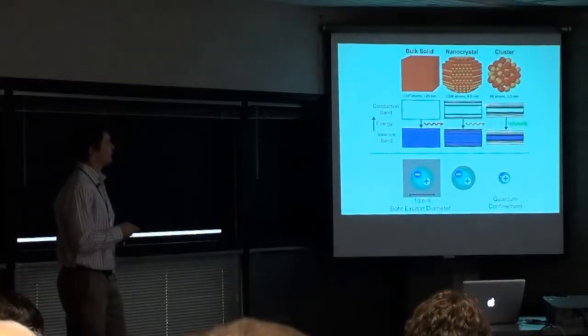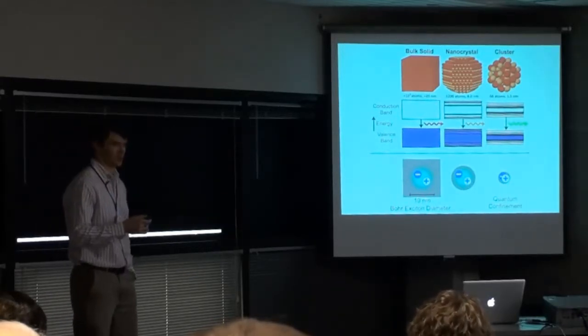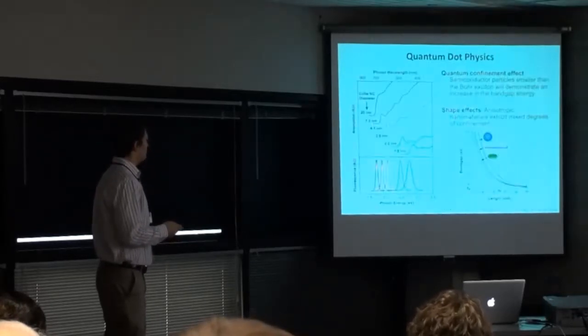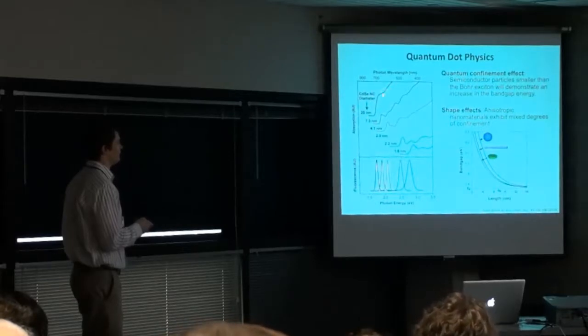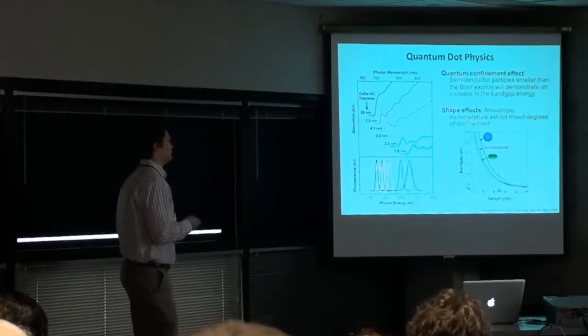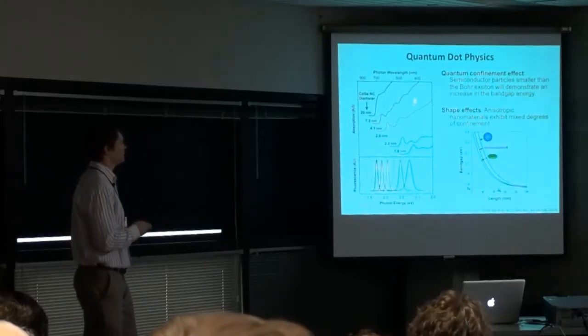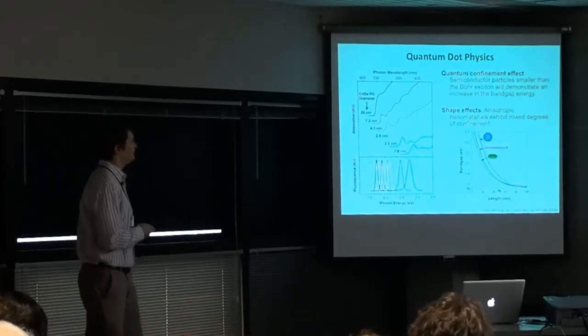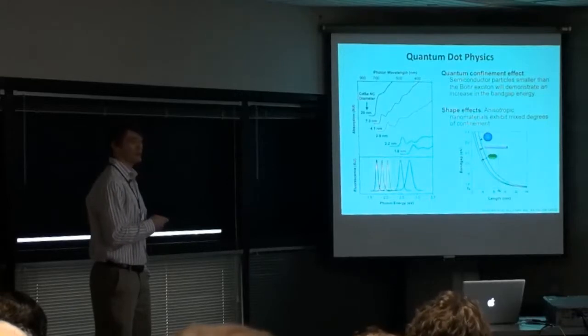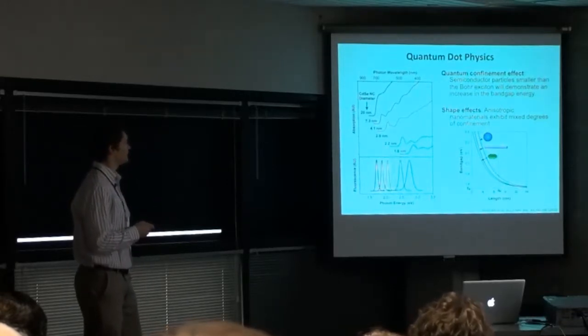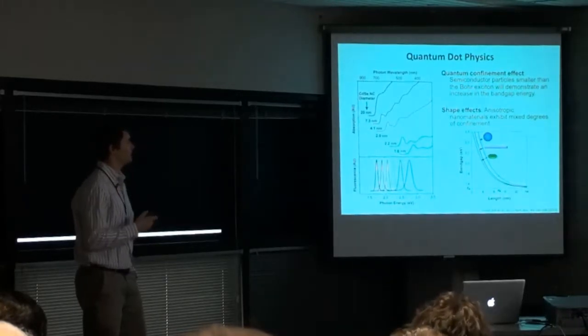As these crystals get smaller, you get more discrete electronic energy bands, because it's becoming more like a molecule or atom with less electron sharing. In the spectrum, a bulk cadmium selenide material has a pretty amorphous absorption spectrum. As you make nanocrystals smaller than the exciton diameter, you see discrete electronic transitions and the band gap of the lowest excited state transition increases. Likewise, the fluorescence emission can be tuned to higher energies, corresponding to lower wavelengths. This is called the quantum confinement effect — altering optical properties, specifically the band gap, depending on material size relative to the exciton diameter.